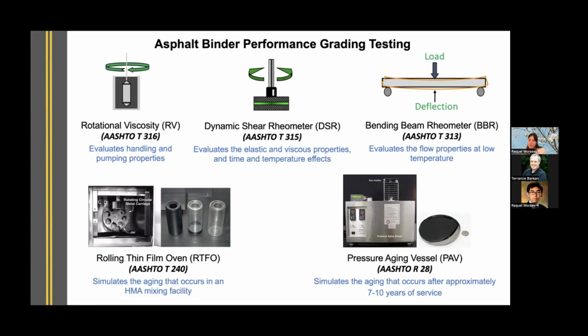Then we use the dynamic shear rheometer, AASHTO T315, to evaluate both the elastic and viscous properties of the asphalt binders at different times and temperatures. Then the bending beam rheometer per AASHTO T313 was used to evaluate also the flow properties at low temperatures. And below in the slide, you can see the two protocols for aging that were considered in the study. A rolling thin film oven per AASHTO T240 that simulates the aging that occurs in a hot mix asphalt mixing facility, and the PAV, the pressure aging vessel, per AASHTO R28 that simulates the long-term aging of the pavement after being exposed, let's say, between 7 and 10 years in a road.